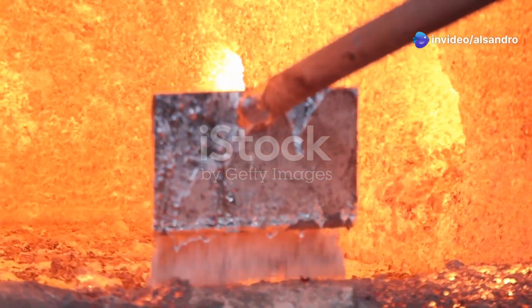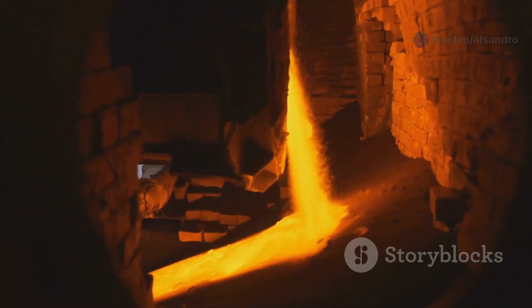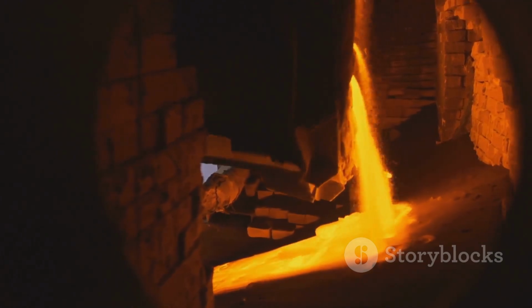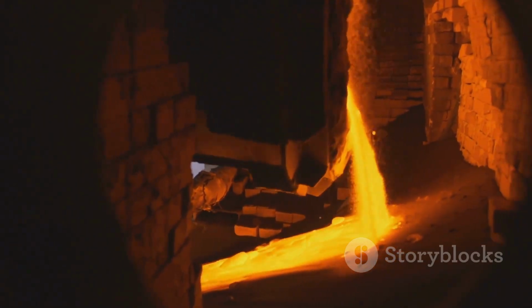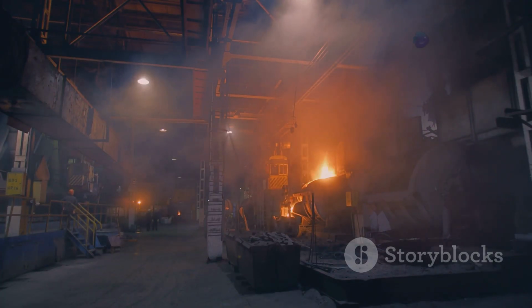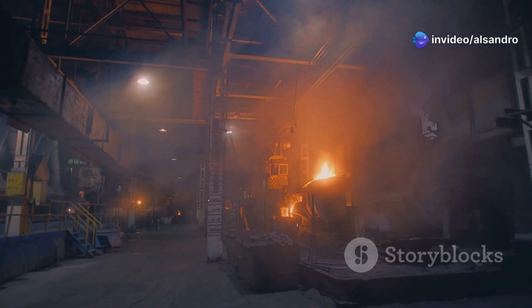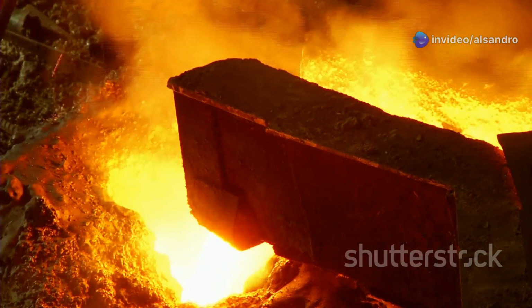Beyond efficiency, slag buildup can wreak havoc on the quality of your final cast iron. As the molten metal churns and moves inside the furnace, it can catch pieces of that hardened slag from the walls. These bits can get trapped in the iron as it's poured into the mold. When this happens, you get what are called slag inclusions in your finished casting.